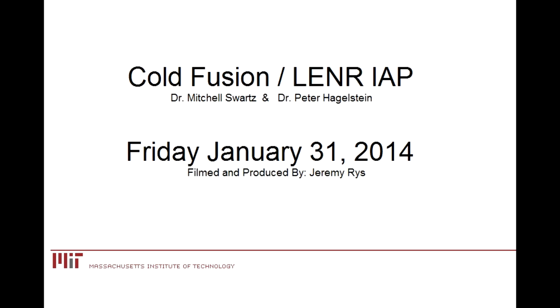Okay, so is nickel hydrogen like palladium deuteride? I'm wondering whether Piantelli's gas loading nickel hydrogen is like the palladium deuteride experiment. We were arguing that in the Fleischmann Pons experiment, the whole point of the protocol could be interpreted as making Fukai vacancies for co-deposited palladium at loading above 0.95 on the surface. In Piantelli's experiment, according to this interpretation, the cycling is making Fukai phase vacancies, and making a lot of them.